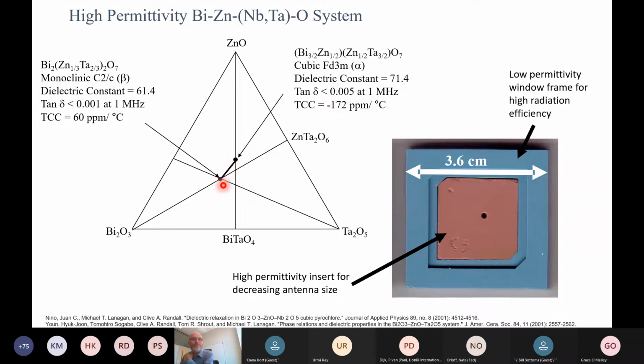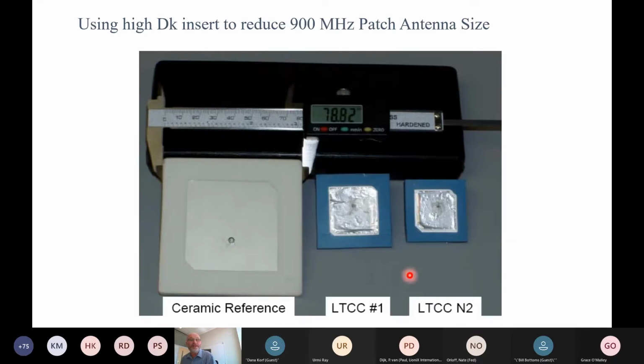And so as we started playing around with compositions between these, we were able to tailor that to get a very low temperature coefficient near 0, but also have a decent permittivity for miniaturization and low enough loss as well, and compatible with some of the processes we were looking at for this antenna. Just to give you an idea, this was a patch antenna with aluminum oxide. I think this was in the 600 megahertz range, and we were basically miniaturizing that with this high permittivity material. So just to give you an idea, oh sorry, it's 900 megahertz. Just to give you an idea of what can be done again with higher permittivities and miniaturization.